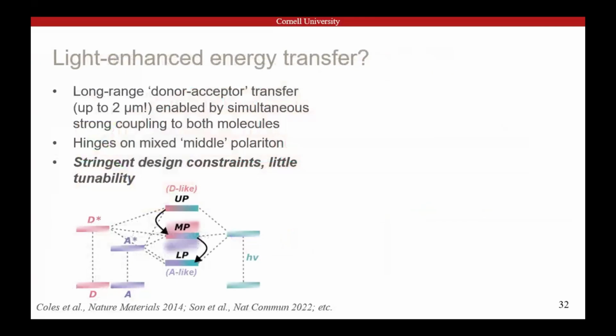I'm just going to quickly take you through a model system where we can start to see some real design principles for how to use polaritons productively. And we wanted to start with the most reproducible and best understood interesting concept in polaritons, which is long-range energy transfer. So it's been known for a long time, if you put a donor and acceptor molecule into the same cavity, they can simultaneously hybridize with the photon to form this ladder of polariton states, a lower polariton, which is mostly acceptor-like, an upper polariton, which is mostly donor-like, and a middle polariton, which strongly mixes the wave functions of the two.